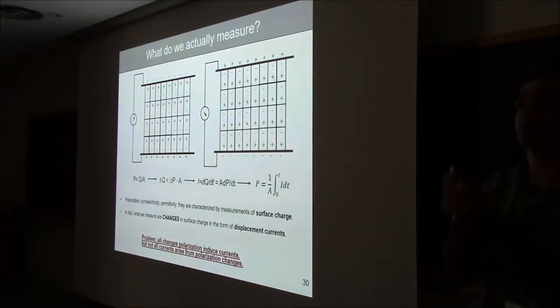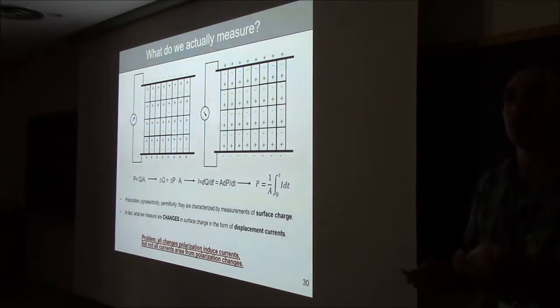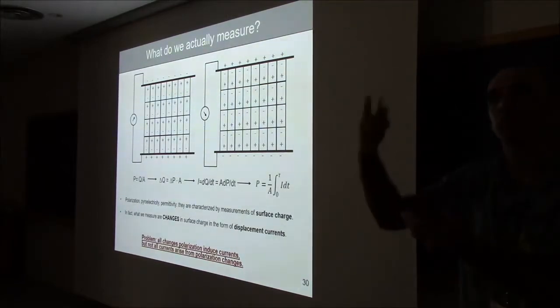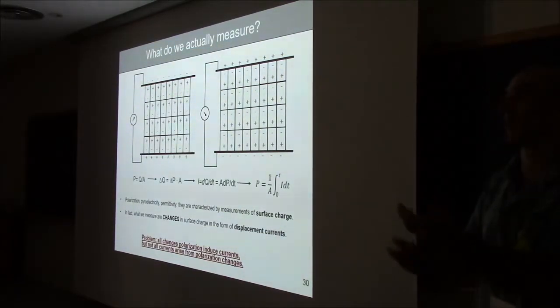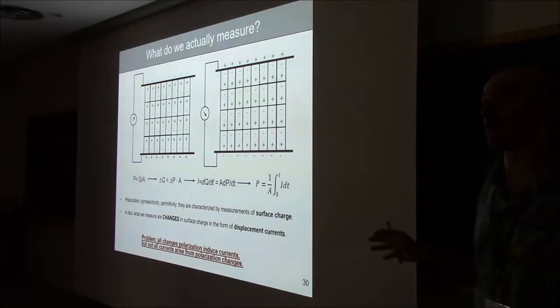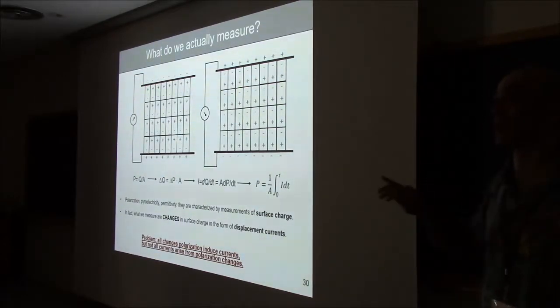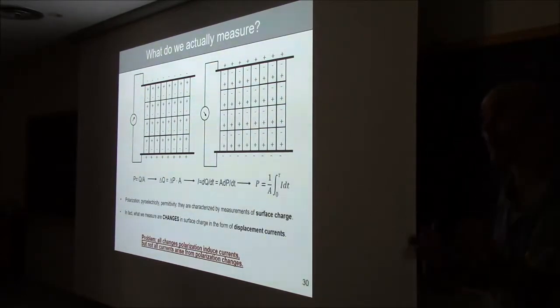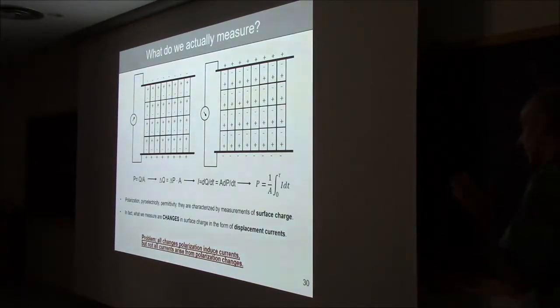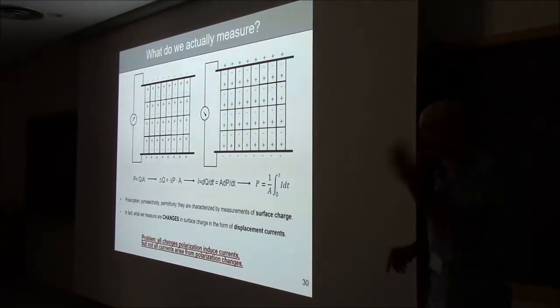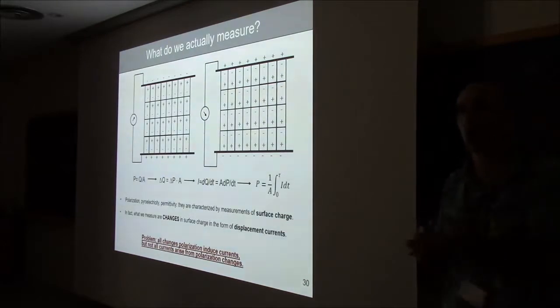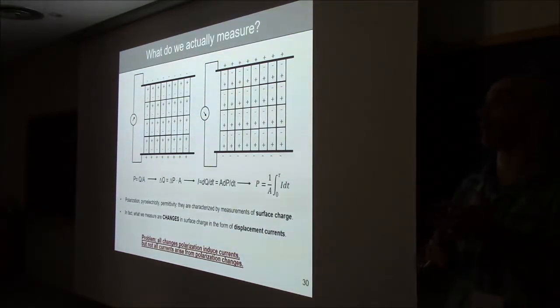Why? Because if your material is a semiconductor and you apply a voltage, you may switch the polarization, but you may also induce some leakage current. And this leakage current has nothing to do with ferroelectricity. And you have to be able to distinguish the two. This is very, very important for this audience because I presume some of you are not coming from the ferroelectrics area but from photovoltaic area.